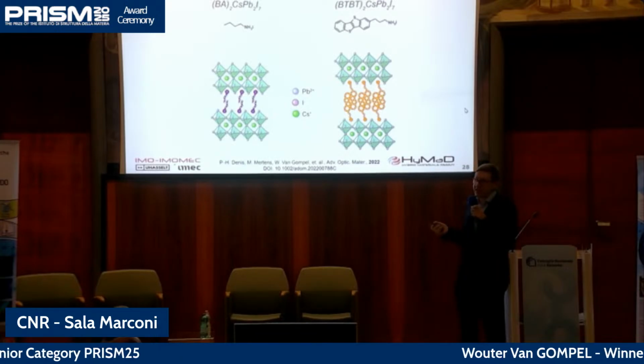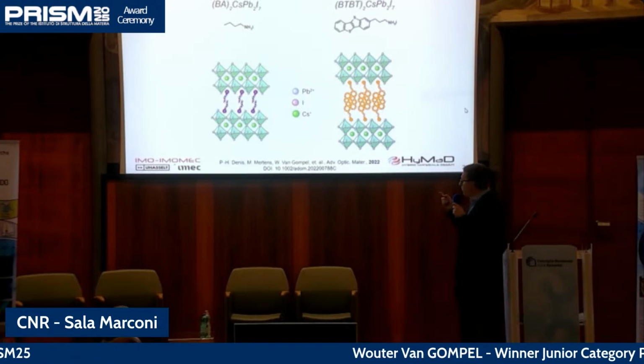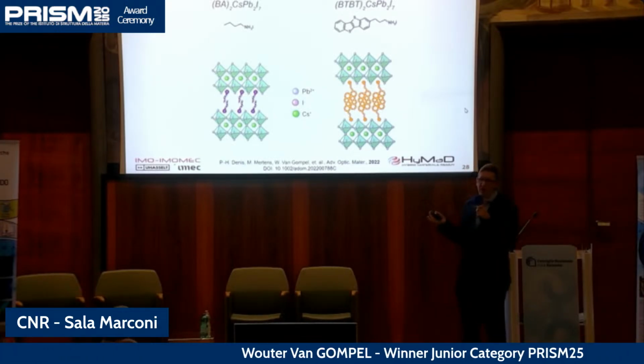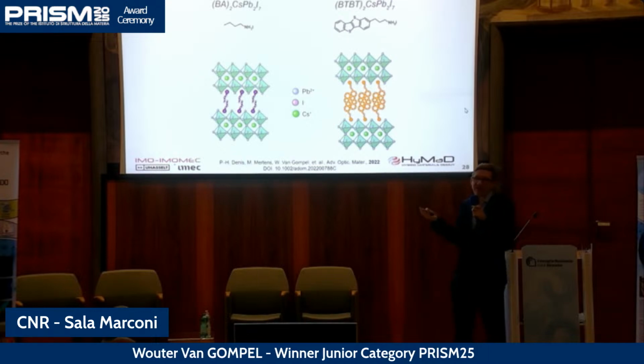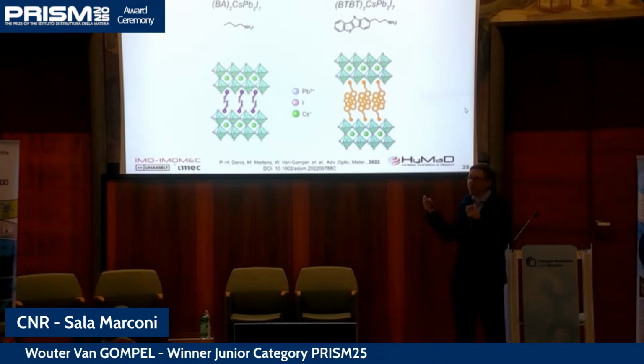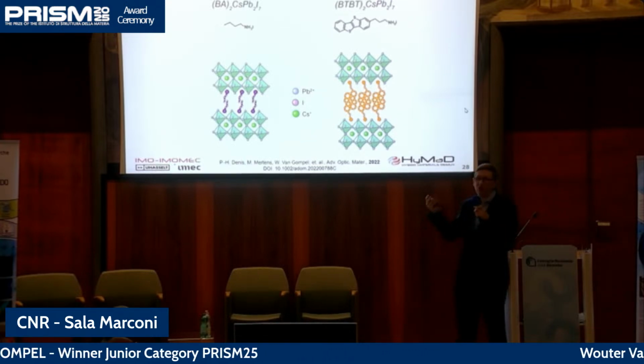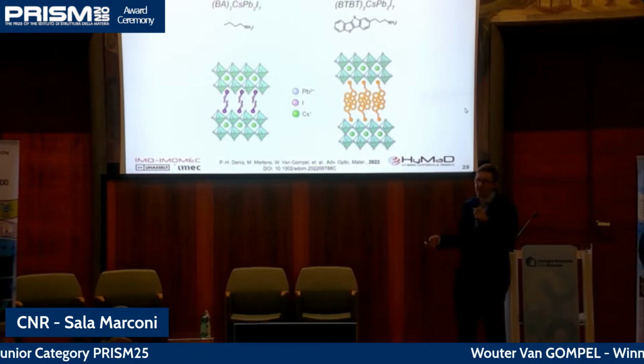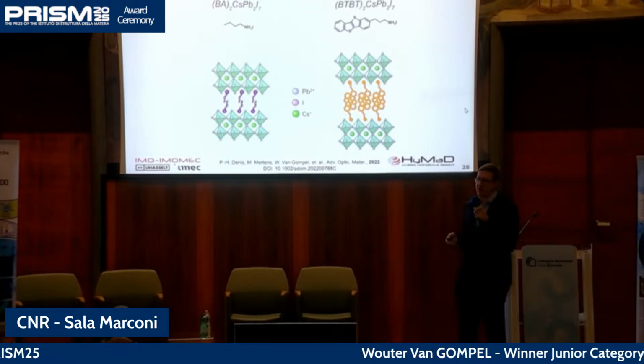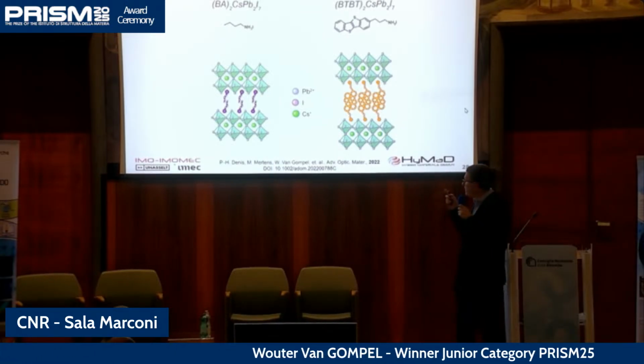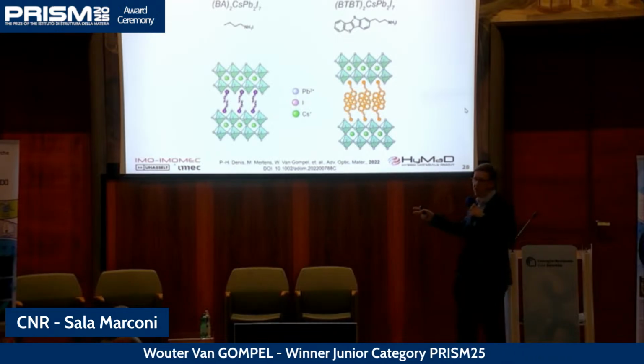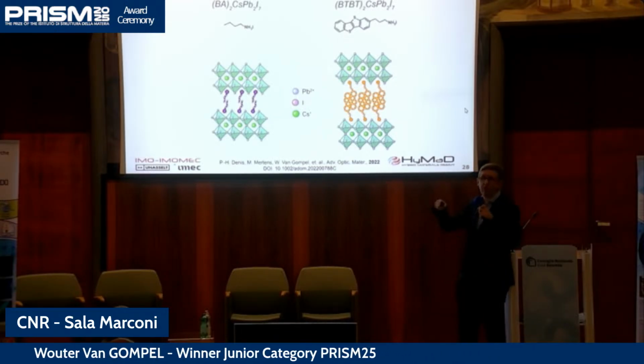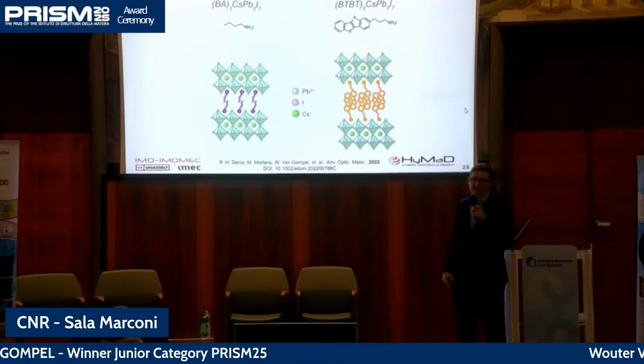In this case, this is now an example where we don't have the crystal structure, but of course, if you have the crystal structure via single crystal X-ray diffraction, for example, then you can prove that it's a real 2D perovskite and not something else. But it's indeed something that you need to be careful of if you are going to design this kind of bigger molecules, that you don't go to even lower dimensionalities. So that's a good point.